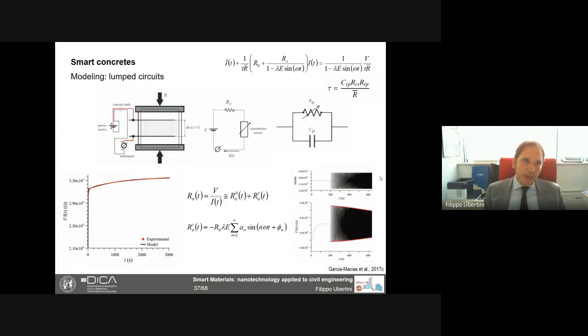Another approach we have proposed for modeling the behavior of these sensors is by doing lumped circuits. Lumped circuits means that we want to reproduce the behavior of these sensors by using resistors and capacitors in series and parallel, so equivalent circuits. And these are very good if we want to reproduce the dynamic response of these materials, like when we do vibration measurements. Because for the overall properties, micromechanics is better, but for dynamics, we need to add time into the problem. And the best way we found to do this was with equivalent circuits.